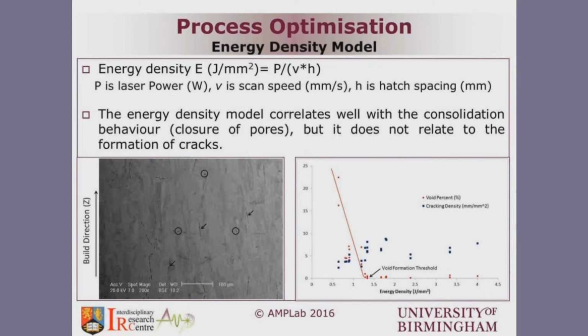But the second factor is cracking, and we do not see significant correlation between the cracking density, the blue squares, and the energy density. It seems quite random in this equation. So that approach gives an idea about a starting point for how much energy we need for consolidation, but it doesn't correlate much with cracking density.